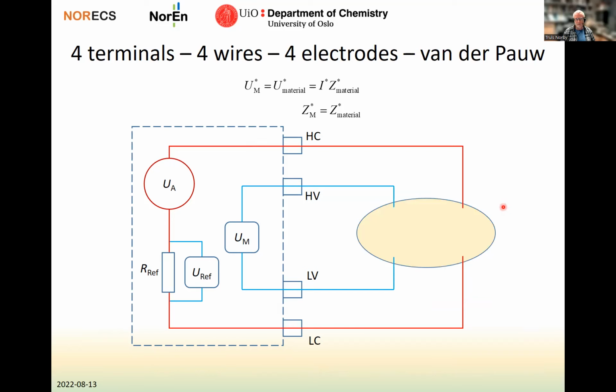There is another type of 4-electrode measurement called a van der Pauw geometry. You can have a disk sample of some kind, and you can contact it with 2 current probes and 2 voltage probes. There's now current running here, and there are current lines going all the way through the disk. It's picked up by the voltage probes here.